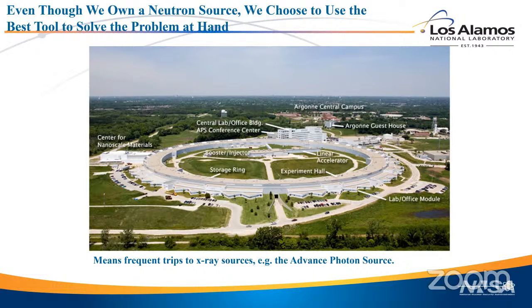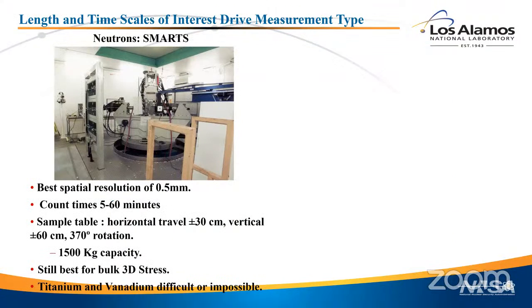So the probe particle that we tend to use depends a lot on the problem we're trying to solve. It depends on the kinetics of what we care about. Neutrons are inherently slow. You only get so many neutrons out. It's limited by heat flow and things like that. The neutron measurements in general are slow. They look at bulk amounts of material. My neutron beam might be anywhere from a couple millimeters to a centimeter big. So I'm looking at cubic centimeters of material and averaging over all of the grains in that cubic centimeter.